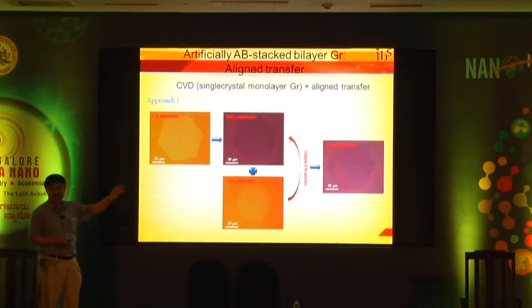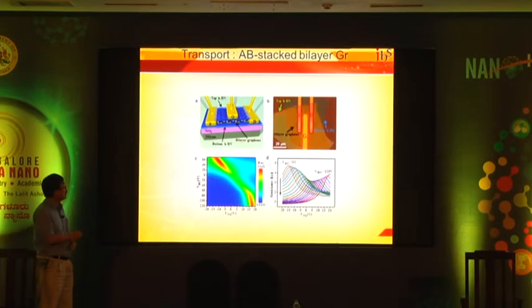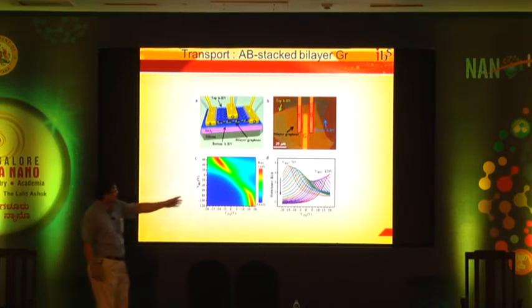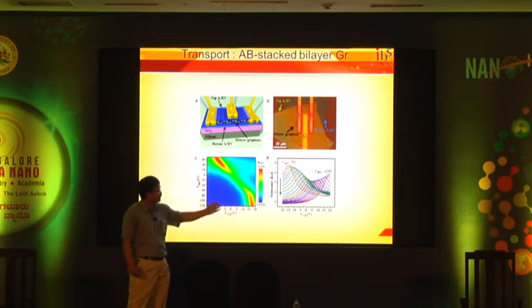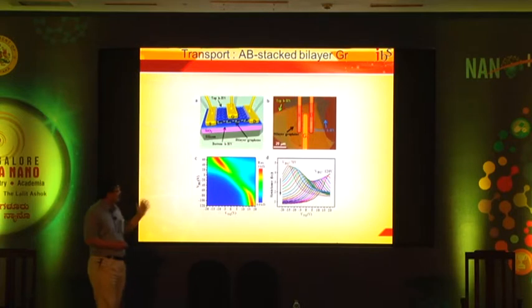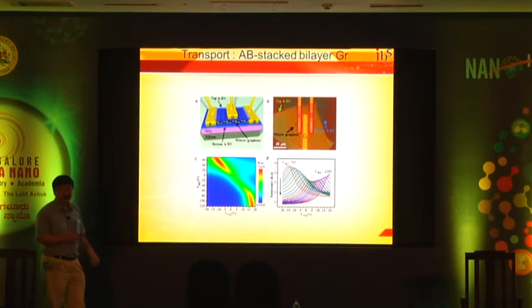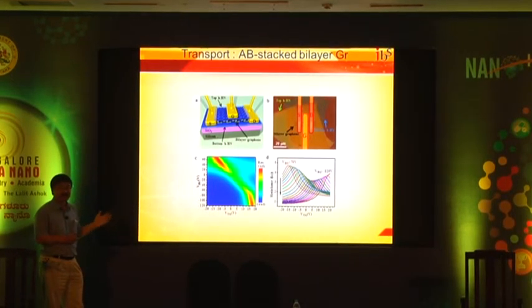This is the dry transfer process. So we don't have any dirty PMMA in between this interlayer. So we have a very high quality bilayer. And once you have this bilayer, we can simply fabricate the device. And then you can see the threshold voltage consistently varies. That means we do open the band gap with this AB stacking order. So this clearly indicates that our AB stack bilayer graphene quality is very good.